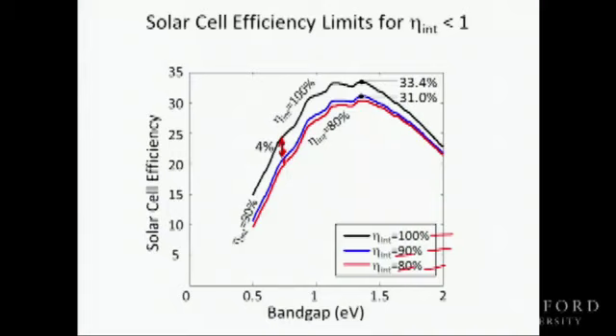Remember, I was disrespecting the small band gap solar cells. And notice the small band gap solar cells, well, it looks like they might be pretty good down here. But notice how vulnerable they are. So here, you have a tremendous loss in performance if you don't have 100% internal fluorescence yield. Whereas the big band gaps, you have a loss, but it's not very significant. So there are some ideas out there for using the small band gap solar cells. They lack robustness, because if somehow you have to compromise and you don't have well over 90% internal fluorescence yield, they perform badly very quickly.